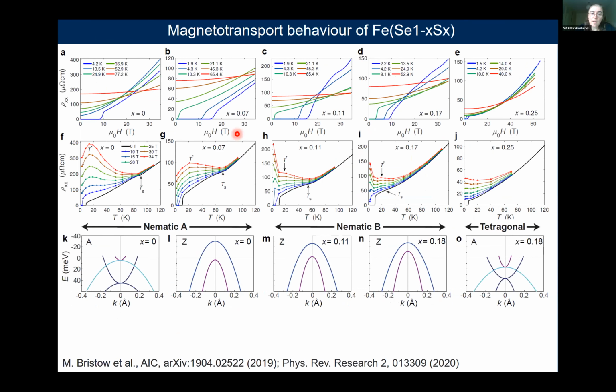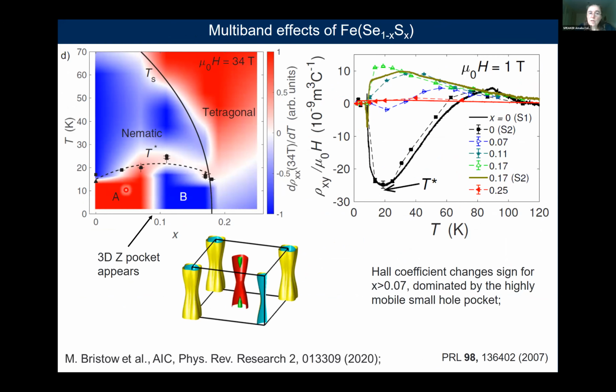in transport, as I mentioned, we do find unusual behavior. This is also in high magnetic fields inside the nematic phase. There's significant magnetoresistance developing for the systems which are nematic, compared with the B² dependence as expected outside in the tetragonal phase. And this change in magnetotransport seems to be correlated with the changes in the Fermi surface. In particular, the appearance of this 3D pocket causes this change in slope in high magnetic fields. This is at 34 Tesla, and also the sign change of the Hall effect.